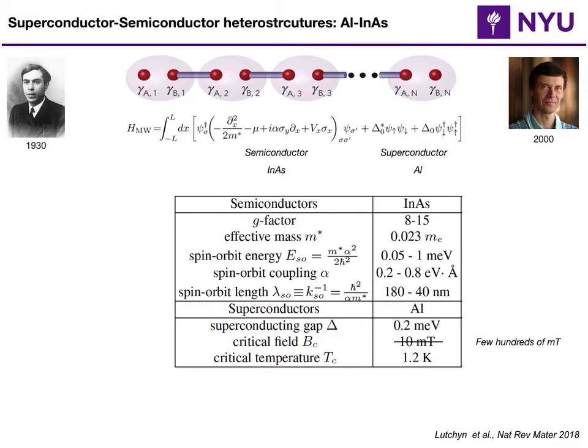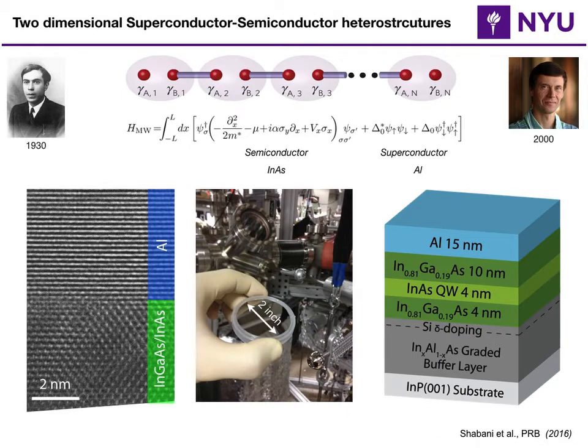And for indium arsenide and aluminum, I've listed these parameters taken from this review article. And it turns out the challenging part is trying to get these states in the presence of magnetic field. That means the superconducting gap is going to deteriorate. So the higher critical field we have, it's to our advantage. Aluminum critical field in bulk is actually very small. It's a type 1 superconductor. But if you make it very thin, you can actually get really high critical field in the plane, right? And it turns out that's the direction that works for this Hamiltonian too, so that would be great, right?